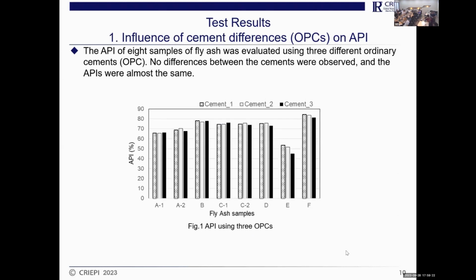And firstly, I show you the test result. This shows the impact on the API value of the difference of the cement. We applied 3 cements, named cement 1, 2, 3. The vertical axis shows the API, and the horizontal one shows the sample number from A1 to F. The reactivity shows much difference among those. But the differences between the cement types are very, very small. So I think the difference of cement has less impact on the value of the API.